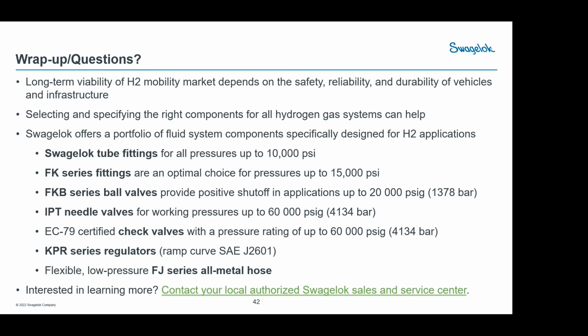One question that was submitted earlier is: what challenges are presented by thermal changes in the H2 fueling system delivery process? Oh, it's a great question, because during fueling, I'll use the example of a 700 bar system. In order to get the maximum number of molecules on the vehicle for fueling and do it within a reasonable time, a vehicle would pull up, and ultimately it's going to have 700 bar in the tanks when it's done. That's the plan. So let's say it comes in with 20 bar, so pretty empty, and pulls up to a station. The station's going to plug in, and the first thing it's going to do is a leak check, which is actually something really cool in hydrogen: we do a leak check every single time a vehicle is hooked up to a station, to make sure that there are no leaks in both the dispenser and the vehicle. In fact, there are up to 3 leak checks done on every fueling cycle.